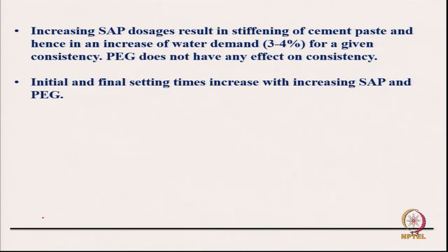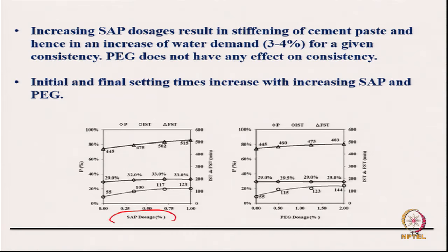So, these are the effects, but these materials you can use them. These are some of those results, SAP doses, super absorbent polymer doses. This is what you call initial and final setting time in minutes. Standard consistency is what is measured, and then you add them and the same amount of water and you find out. So, initial setting time, final setting time, this is what is given here. As I increase the SAP dosage to 1% or so, this is also a small quantity. So, this is what happens, and this is with polyethylene glycol. This is the dosage it shows, and these are the properties, how it will go.